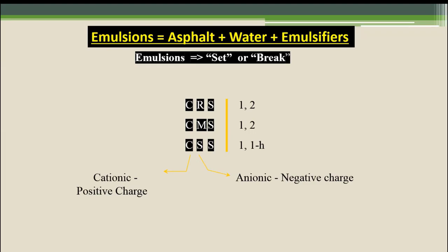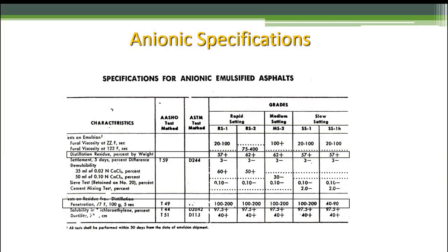If we look at the specification, at the top, this is an anionic, so negative charge, emulsified asphalt. You can see those ranges, RS, MS, and SS: rapid setting, medium setting, slow setting. You see two ranges on RS, RS1 and RS2, one grade on medium set, MS2, and then SS has two grades, and we'll get to that in a second. But the important thing to remember, and what we use emulsions for a lot, is chip sealing and tack coat.